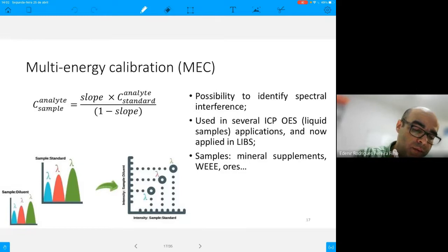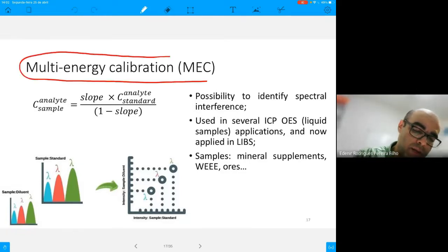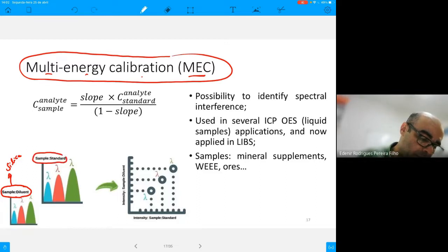One of the most used univariate calibration strategy in LIBS is MEC, multi-energy calibration. In MEC, we have a pellet with sample and a diluent. This diluent can be, for instance, silica, for example, and we have a sample and a standard mixed. We have two pellets. In the x-axis, we have the sample plus standard. We can mix this in a 50-50%. And in the y-axis, we have the sample and diluent.